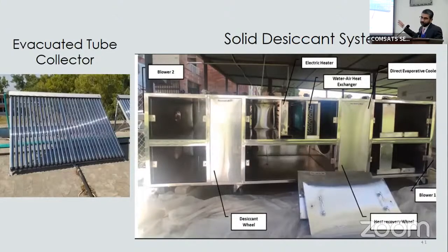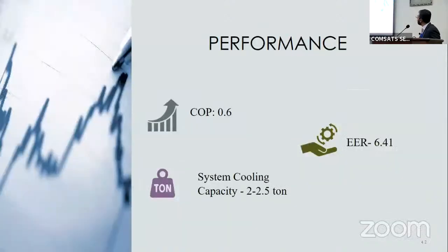This is the solar thermal system which we have developed. You can see we are choosing evacuated tube collectors. They provide us hot water at around 90 degrees centigrade, and through that hot water we achieve air temperature around 70 degrees centigrade. 70 degrees centigrade is enough to regenerate the desiccant wheel, to regenerate the silica gel, to make it possible again to absorb moisture from the air. The other components you can also see here. As far as its current operation is concerned, the coefficient of performance which we achieved is around 0.6.